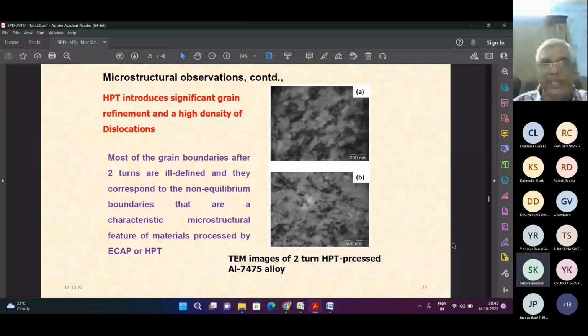These are particularly a characteristic microstructural feature of material processed by ECAP and HPT. If you see most of the images processed by ECAP or HPT, you can see similar types of TEM micrographs. This is the TEM image of 2-turn HPT processed aluminum 7475, an aluminum zinc magnesium alloy. Most of the figures look like that only. Why? Because you get a lot of non-equilibrium grain boundaries, and you can see such type of images after HPT. Next slide, please.